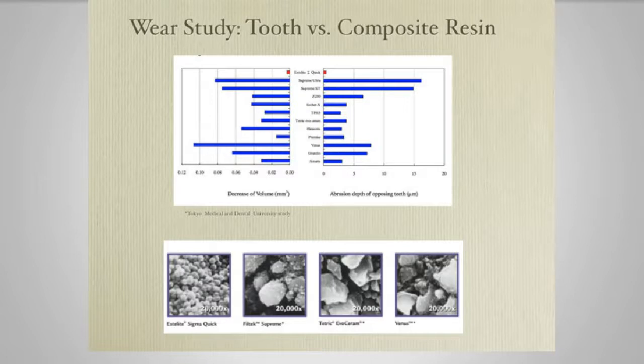So what they did is they took these teeth and placed these different composites on them, and they put them opposing natural tooth structure, opposing another set of teeth. And basically they had them wear across from each other, back and forth for about 60,000 cycles. And then they measured the volume decrease in the composite, and also the abrasion depth on the opposing teeth. And you can see Estelite Sigma Quick did really well in this test.